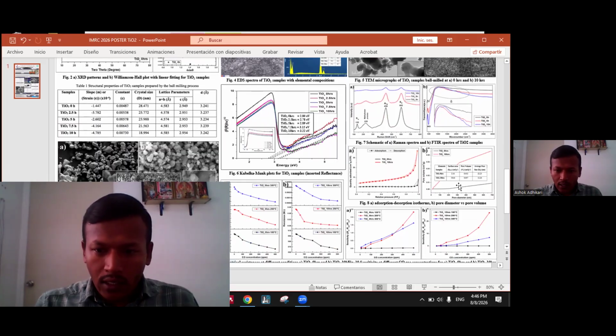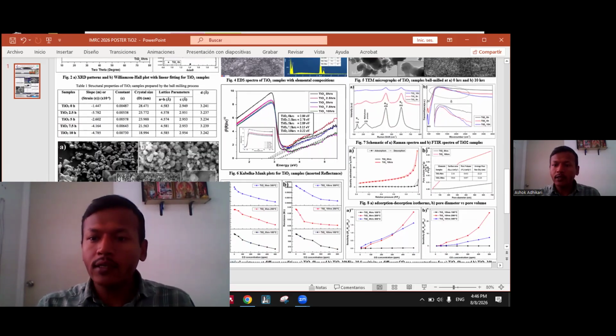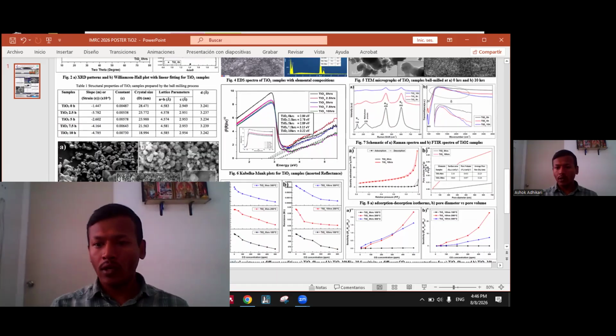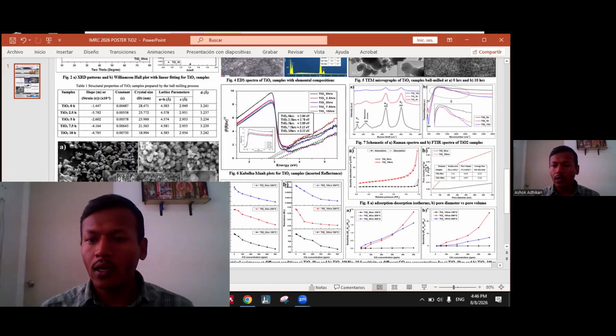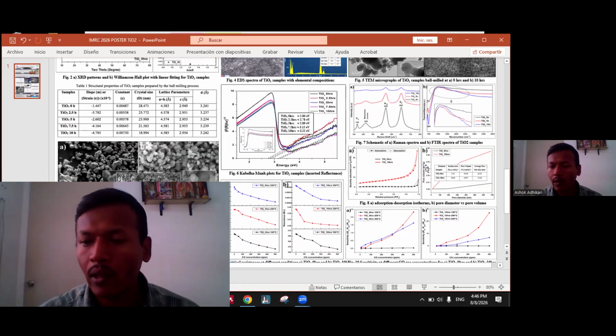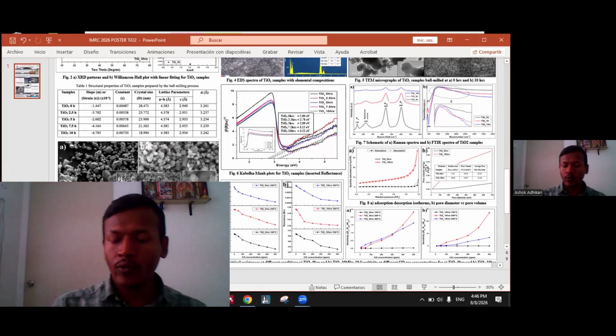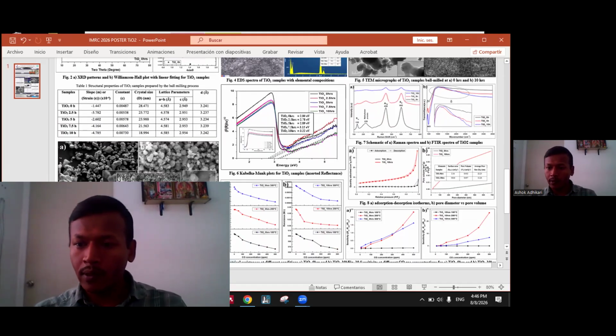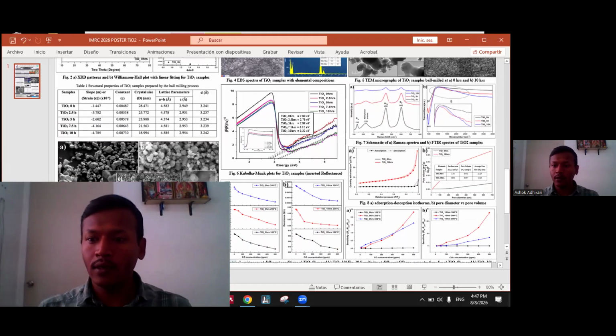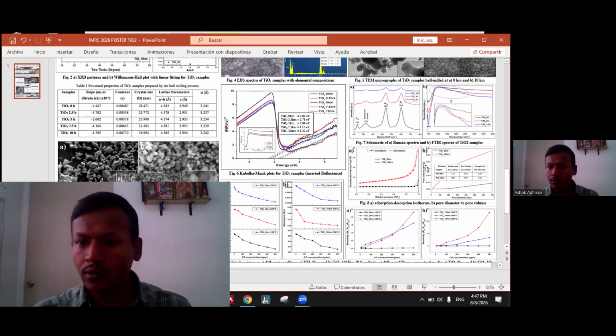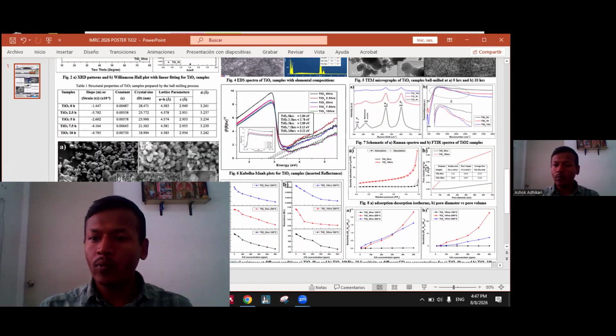And finally, we have also checked the textural properties, which are BET studies, and from here we have the surface area. So for the milled samples, the surface area increases from 2 to 18 square meters per gram, and pore volume and pore size are comparable to, compatible with, mesoporous particles.